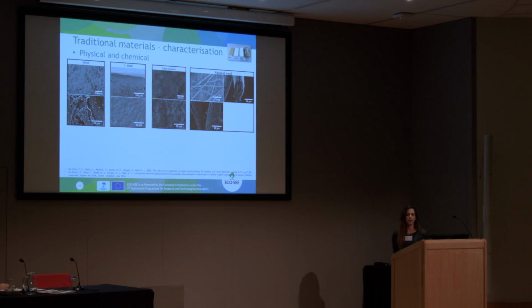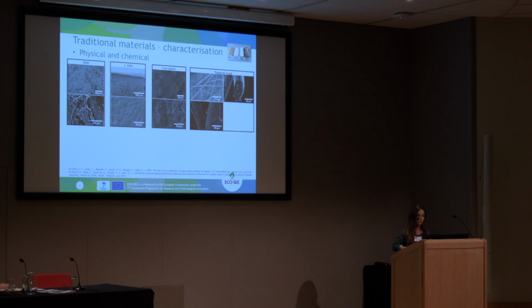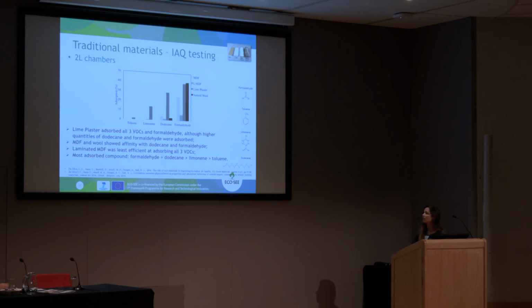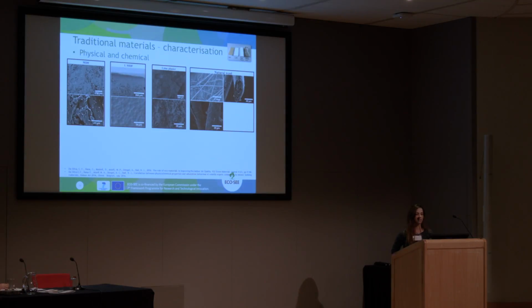So we know that lime plaster performs better than the other materials, but why is this happening? I studied their microstructure to see the pore size of these materials and how the surface is. What we can see is the laminated MDF, which didn't adsorb almost anything, as you can see here. This is because its surface is very flat, so there are no pores. The surface area is very small compared with the other materials. The lime plaster has very small pores and high surface area, and thus the adsorption is very good on this material.